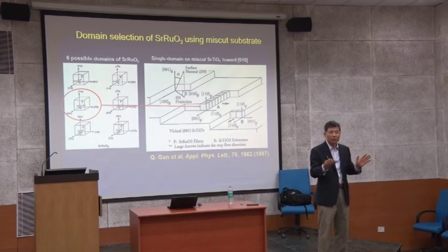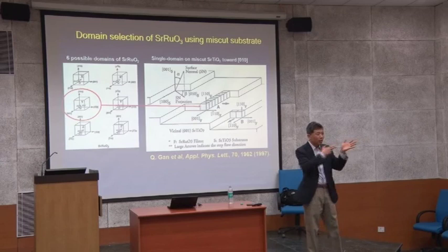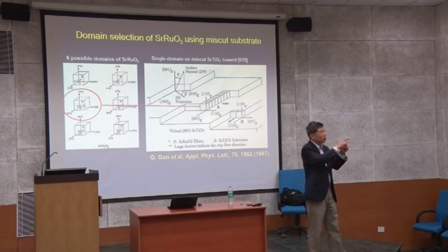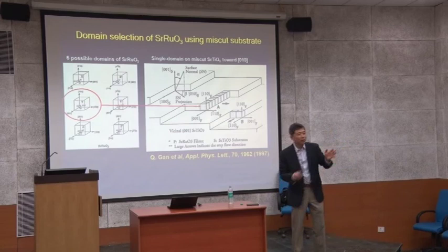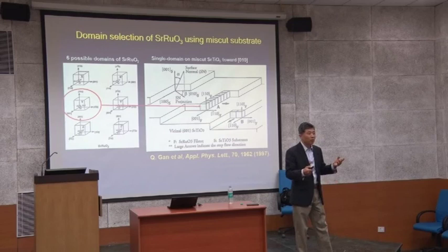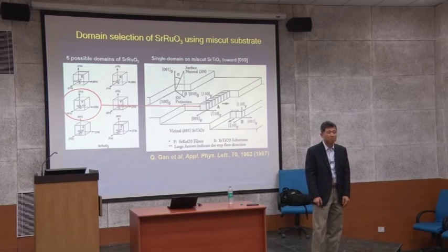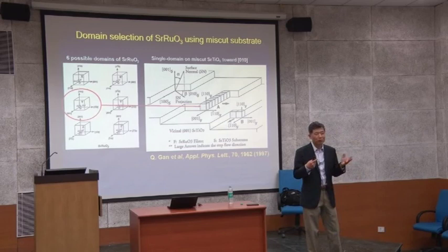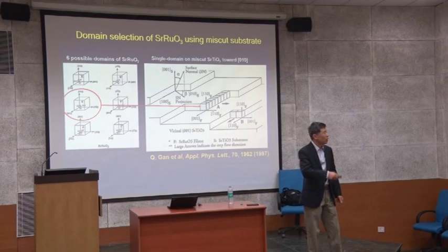So that means you have certain relationships, and you rotate this, then you get the discrepancy between this and the diffraction. When you rotate the phi angle, phi rotation, we align the phi axis as you want. This reflection circle is circling around like this. If the circle gets bigger, it means the miscut angle is big. If the circle is small, the miscut angle is small. If it doesn't circle, and just the one spot stays perfectly the same, that means the miscut angle is zero. Do you understand this very simple one? But you have to do something more complicated in practice. The simple concept is a large miscut, small miscut, and zero miscut.